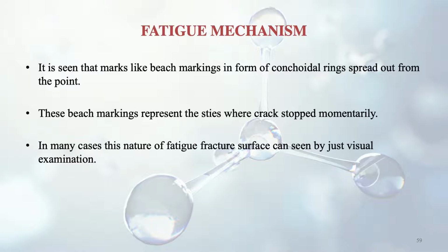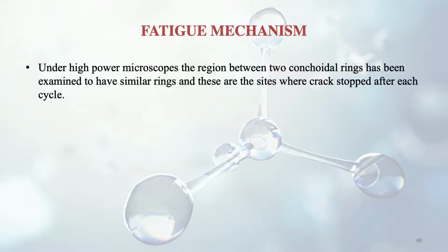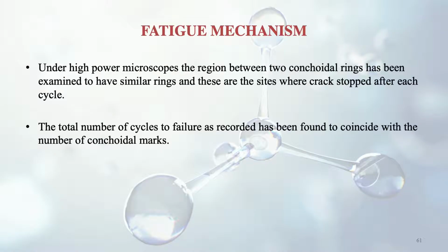In many cases, this nature of the fatigue fracture surface can be seen by just visual examination. Under high power microscopes, the region between two conchoidal rings has been examined to have similar rings, and these are the sites where the crack stopped after each cycle. So we study this with the help of high power microscopes, because only then will we be able to differentiate between two conchoidal rings. The total number of cycles to failure as recorded has been found to coincide with the number of conchoidal marks. So these conchoidal marks are giving us the total number of cycles.